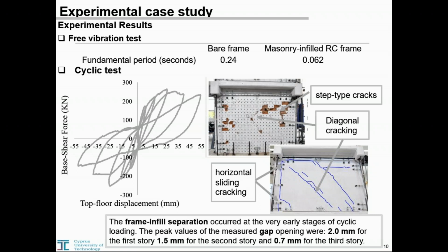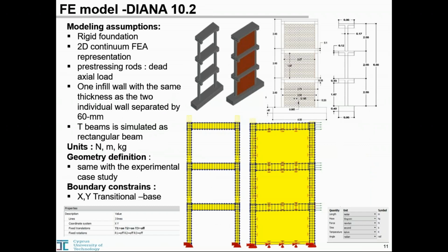The maximum base shear force was obtained during the 3rd cycle of loading of the specimen. After the 3rd cycle of loading, the lateral strength decreased due to local crushing at the 1st story of the infill. During early loading of the masonry RC frame, a cracking pattern developed, as you can see in this figure: horizontal cracks in the corners, diagonal cracking in the middle of the infill, and step-type cracks also developed. The frame-infill separation occurred at a very early stage of loading. The peak value of measured gap opening was 2 mm for the 1st story, 1.5 mm for the 2nd, and so on, as you can see.